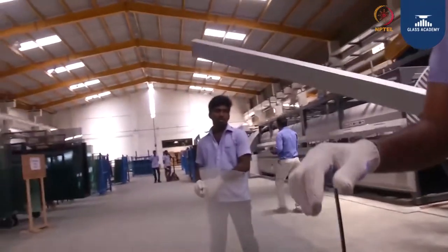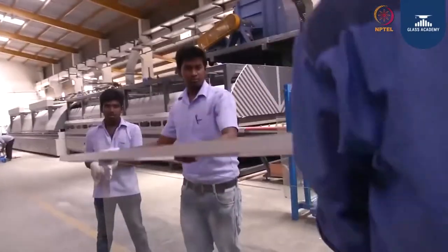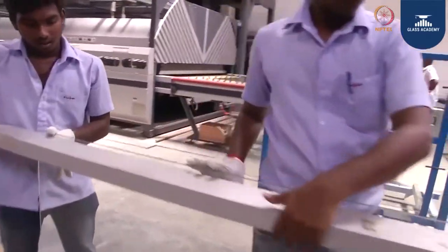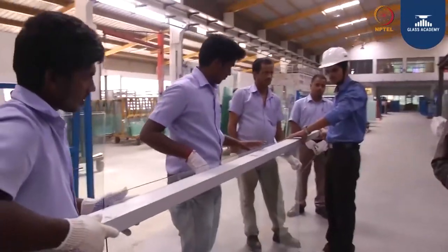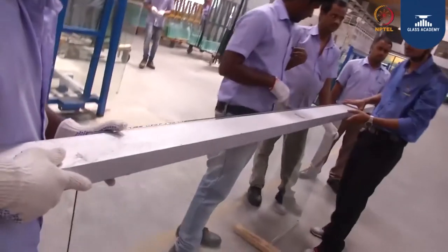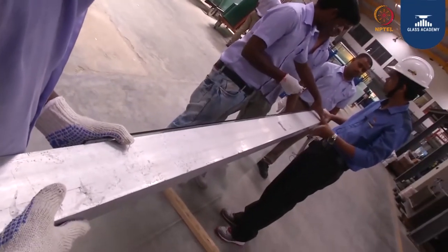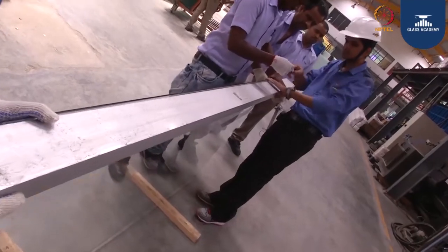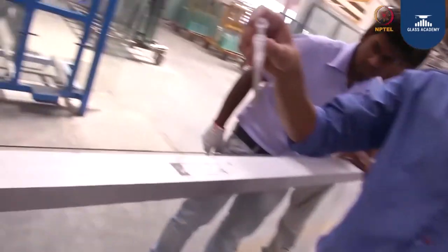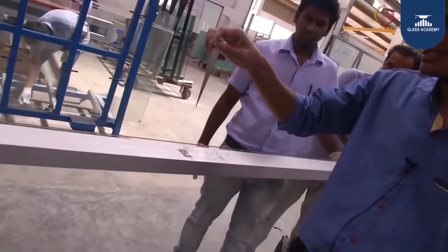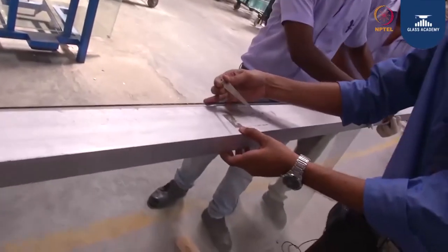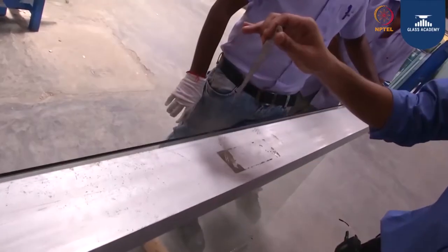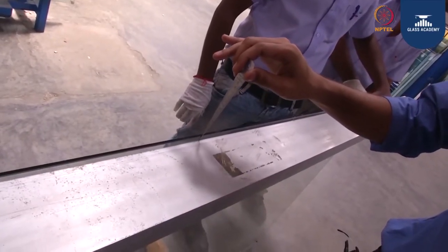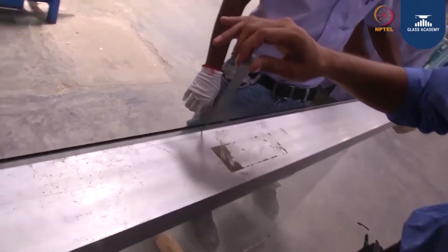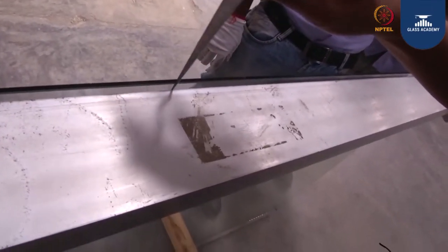Now this is a straight ruler. With the help of straight ruler, we are going to measure the bend in the glass. So this is a taper gauge. This is a taper gauge which will determine the bend levels in the glass. I am going to keep the glass straight, and I am going to measure the gap or the bend between the glass and the taper gauge. If you see, it is coming 1 mm.